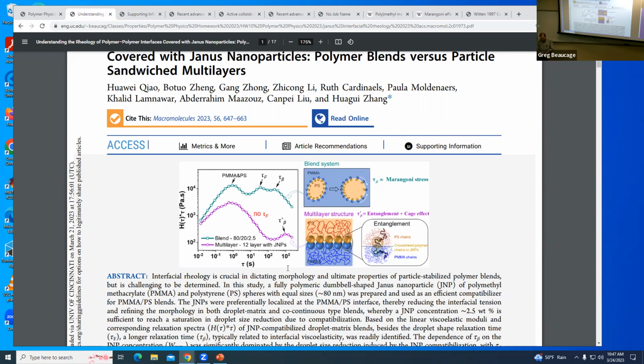He doesn't do that. He goes to the relax stress. He measures the compliance. So he does a pulse and then he watches the thing relax, right? And then he converts that back to modulus. The H is the spectrum for modulus, L is for compliance. And because that's such a slow process, he can expand the frequency range by doing that. So we can get the low end with the compliance, and they can couple this together without